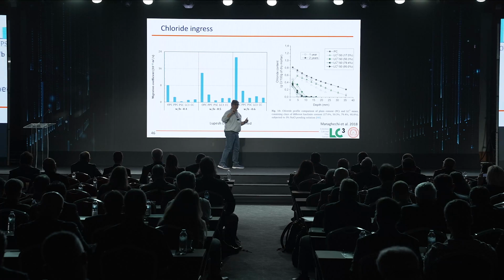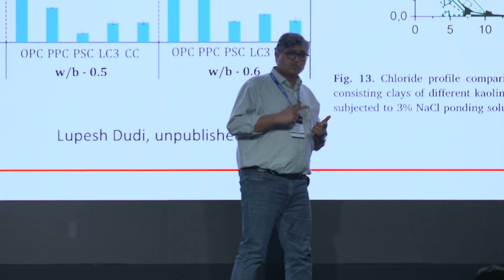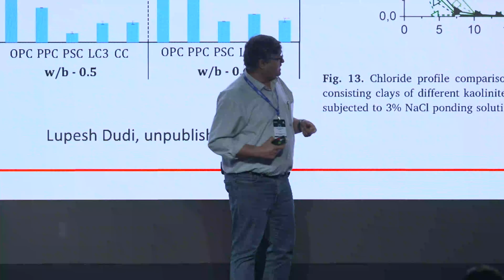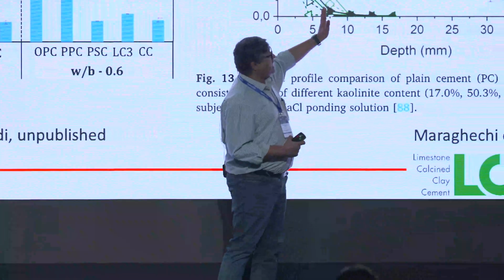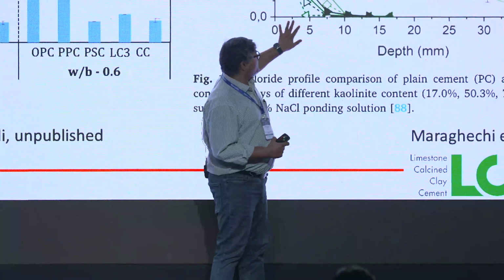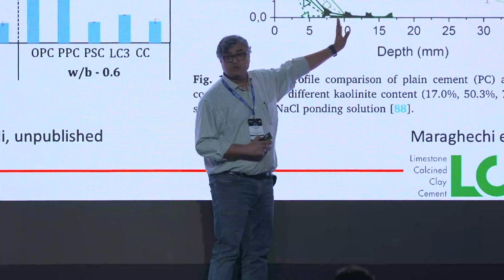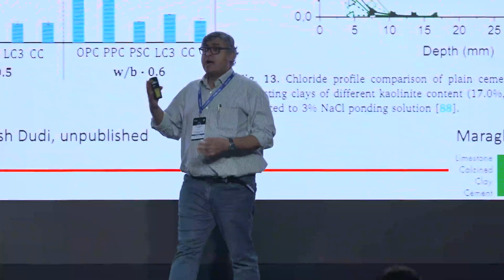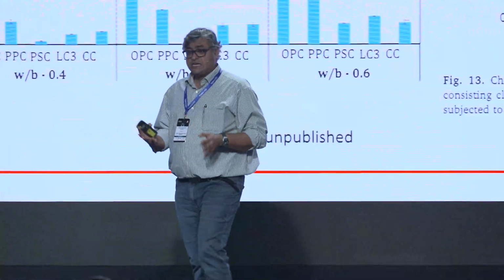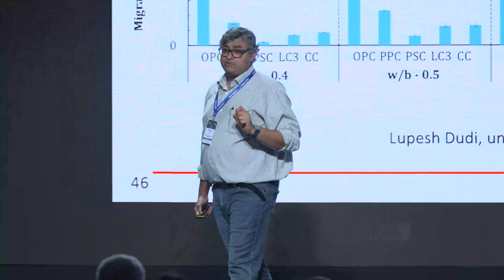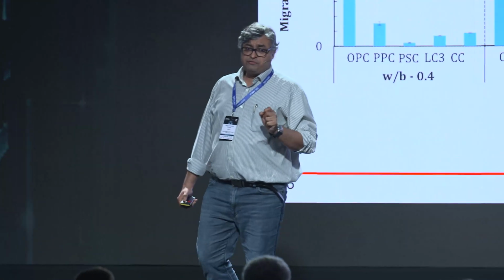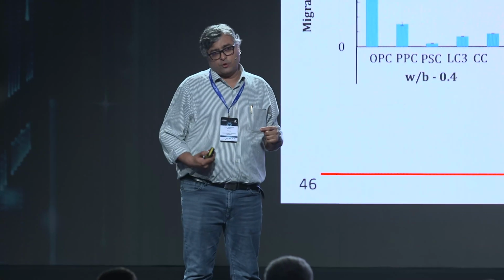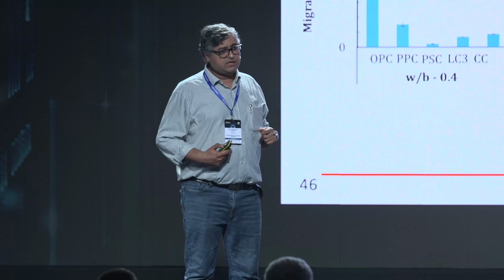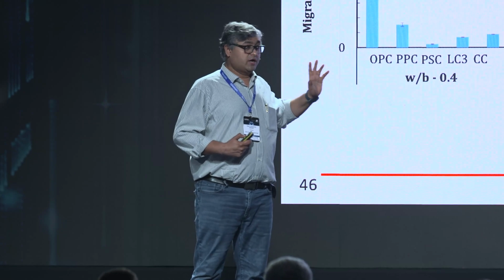Chlorides, one, because of the finer pore structure, second, because of the more efficient chloride binding that you get in the case of LC3, are not able to penetrate beyond the first few millimeters into the concrete. They're just not able to go in. And because they're not able to go in, your steel is better protected. We now have results on corrosion of reinforcement, and of course, you don't see any corrosion because the chlorides are not there. So applications where chlorides are an issue, you just don't need to worry about it.